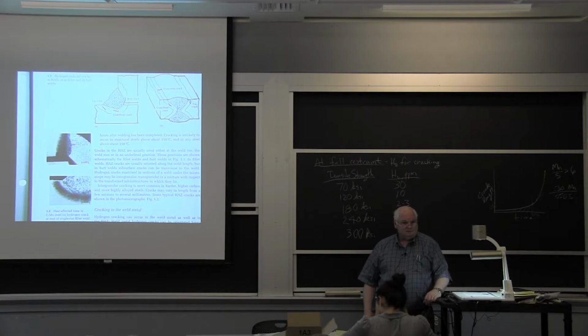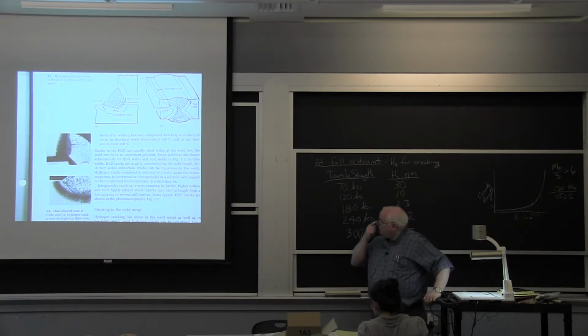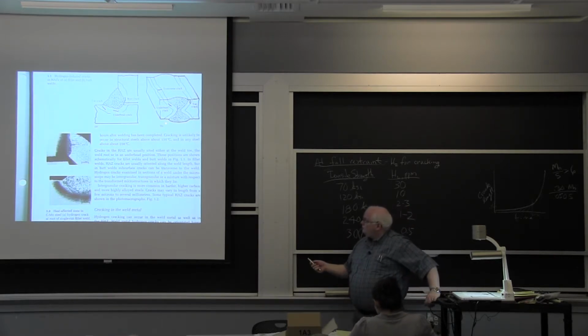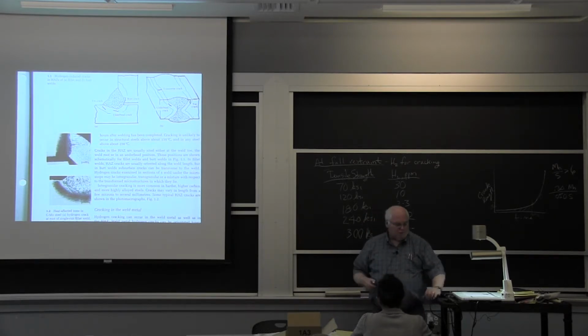Pretty bad. You can't even find it with magnetic particle. You could find it with ultrasonics, but in 1992 the Navy hadn't qualified ultrasonics for the shipyard. And they look like this. Okay, this one is a toe crack, actually did penetrate the surface. But in any case, these are underbead cracks, and it's a problem.